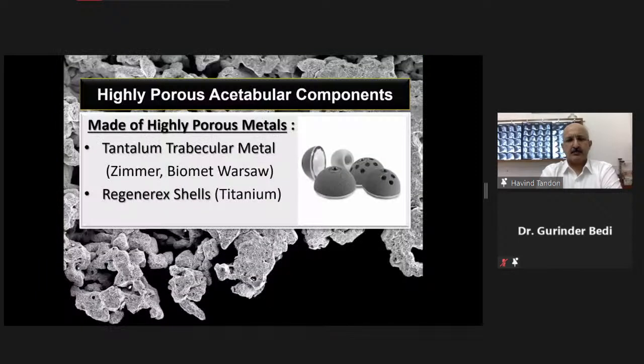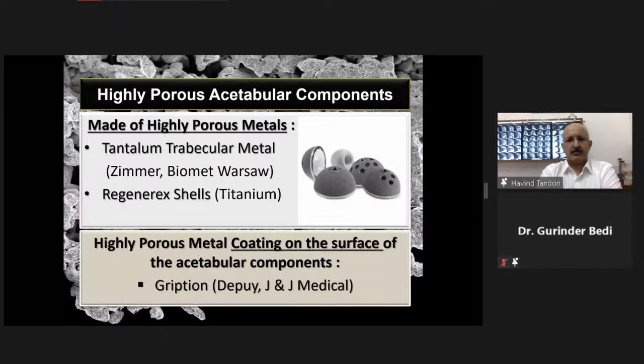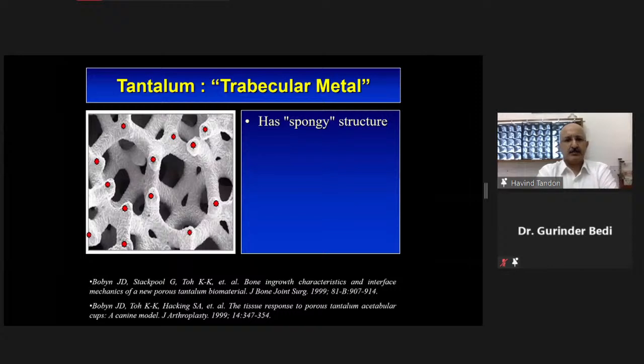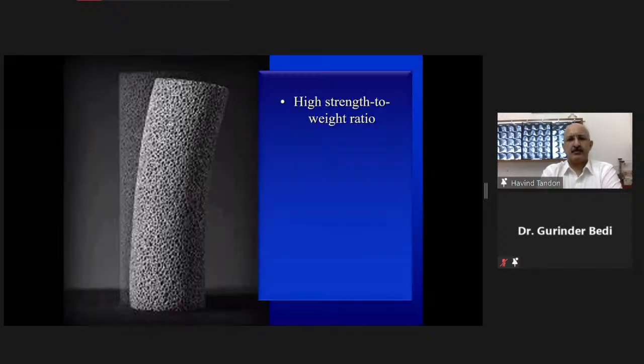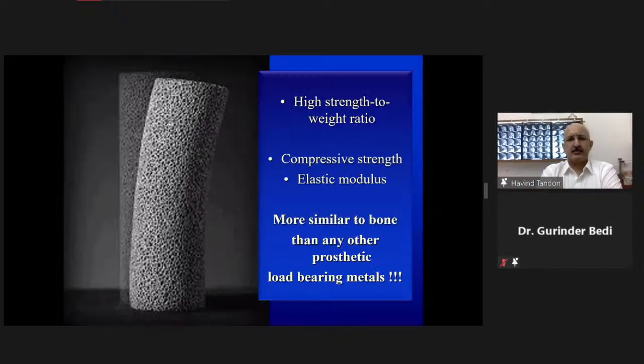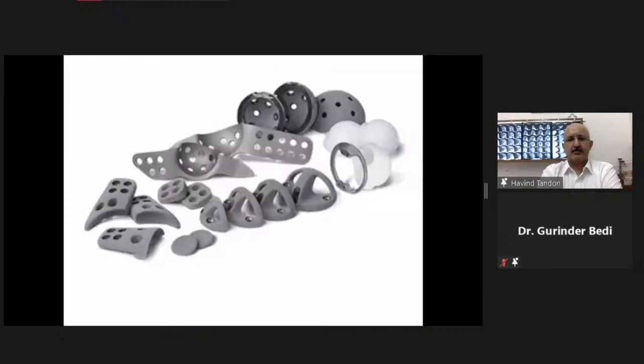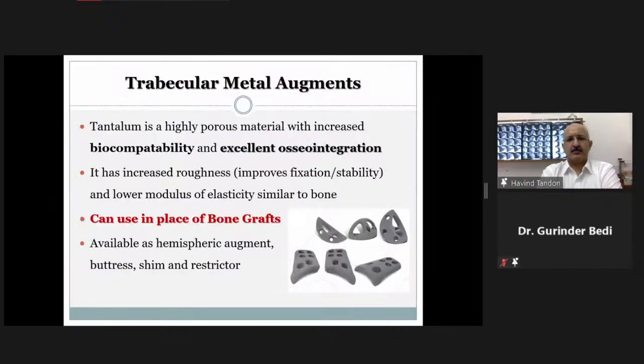You can have highly porous acetabular components made of porous metal itself, like tantalum, or just the coating, as Gurinder told. The most commonly used is tantalum, the so-called trabecular metal, which has great physical properties, more similar to bone than any other prosthetic load-bearing metal. You get all sorts of wedges, augments, shims, buttresses, and cups that you can use in different scenarios, and they can be used in place of bone graft.